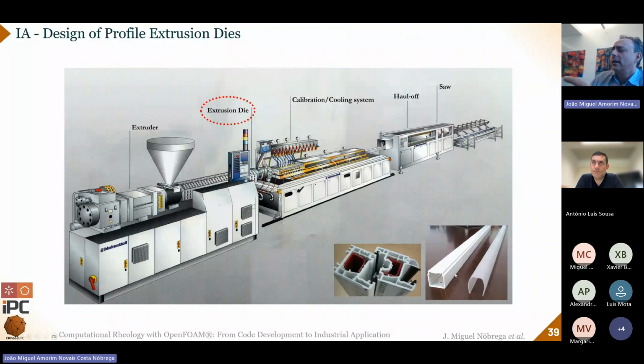Profiles are plastic parts with constant cross-section. The material is placed here in this upper part, then it's melted, and the extrusion die is somewhere over here, and it shapes the profile. Then it has to be cooled down in the cooling system. Then there is a puller that pushes the material at a certain specified velocity, and then there is a saw that cuts the material.